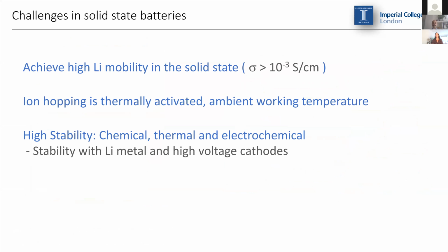So what were the main challenges in the development of solid-state batteries? The first one is that we need to achieve similar lithium mobilities as in the liquid state, whereas in the solid state, ion hopping is thermally activated, and we are working at pretty low temperatures that can range between -10 and 50 degrees C. We are aiming for conductivities above 10⁻³ siemens per centimeter, so 1 millisiemens per centimeter. And also, we need the electrolytes to have high stability, so we need them to be chemically, thermally, and electrochemically stable, mainly with lithium metal and high voltage cathodes, so we can develop batteries that have higher energy density.